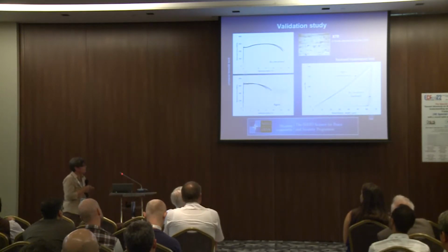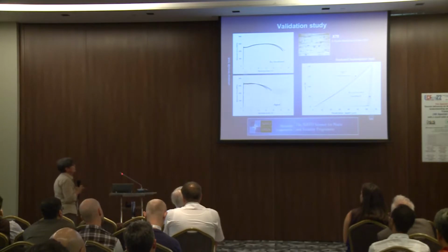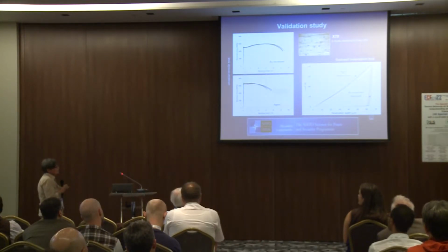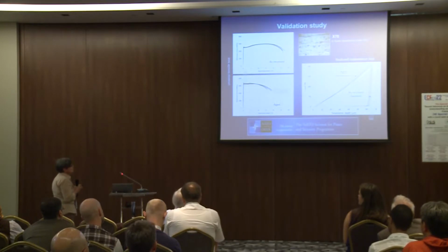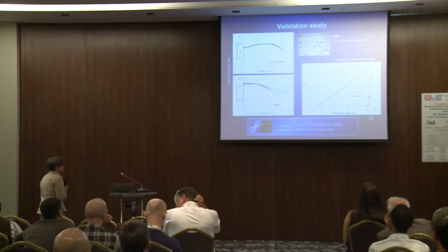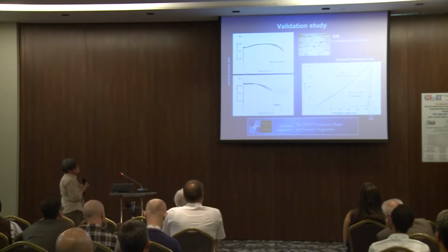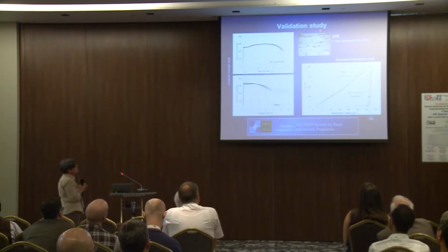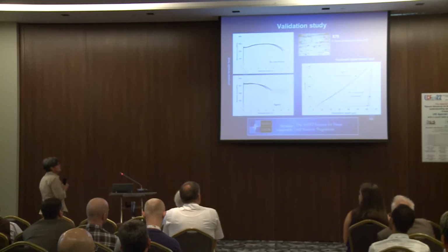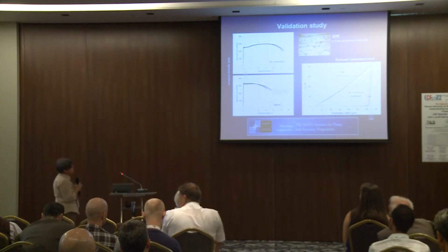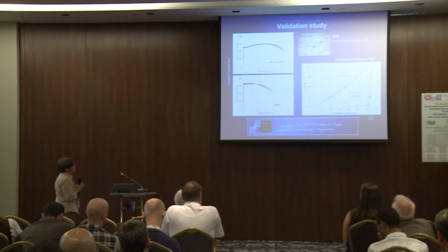So in this phase, we are going to check whether this kind of approach is suitable also for the kind of change of material properties which occurs in degradation of pipeline steels. Here we see another example of experiment carried out, this time on X60 steel. These are the results of tensile tests, which were performed on a tensile sample from the pipe wall.